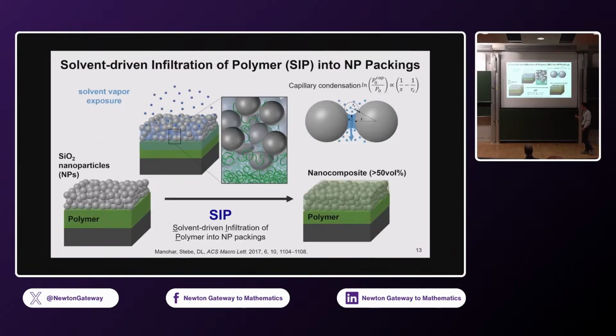All right, let me tell you a slightly different story here. So this is a case, instead of heat, we now use solvent. So we use this acronym, solvent-driven infiltration of polymers. So we take the bilayer, we expose it to vapor of the solvent. Vapor undergoes capillary condensation, and then that induces infiltration of polymer. Now, what we wanted to study here is, how does the effect of the interface, essentially, interaction strengths between the nanoparticle and polymer affect the rate at which the polymer infiltrates into these solvent-filled pores.